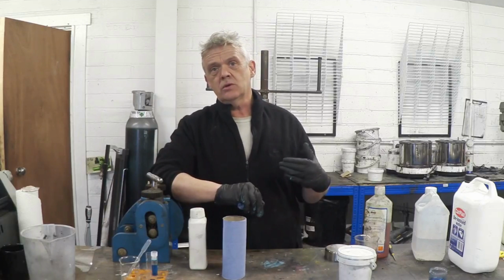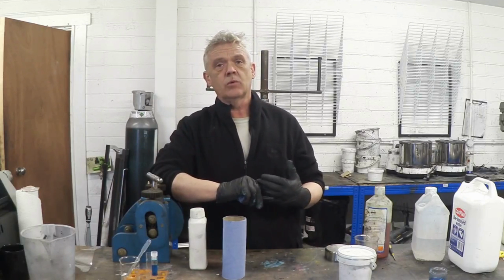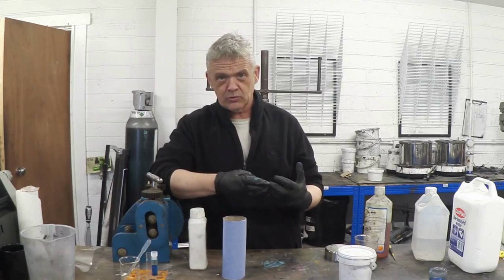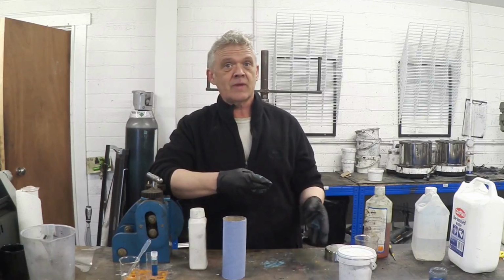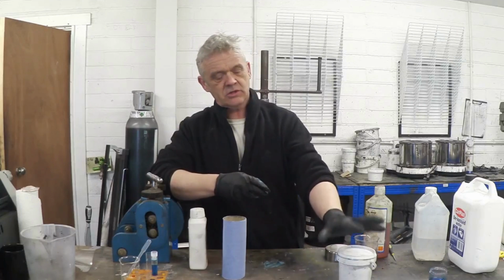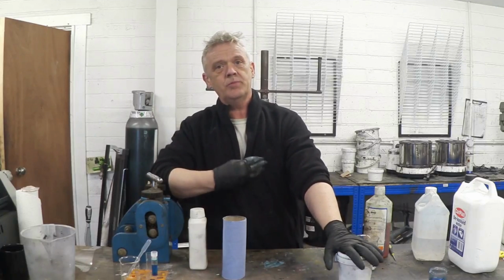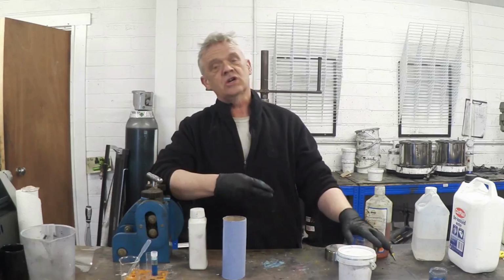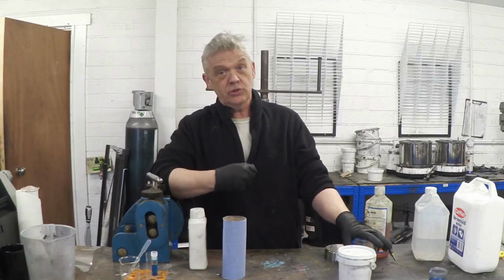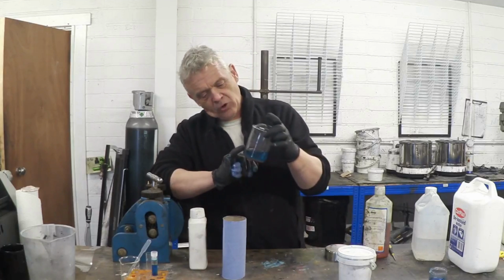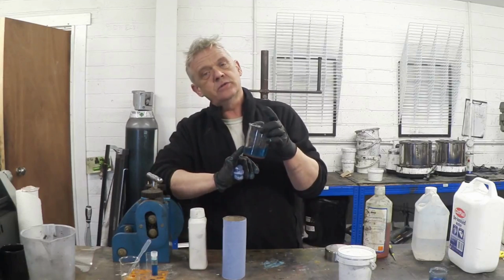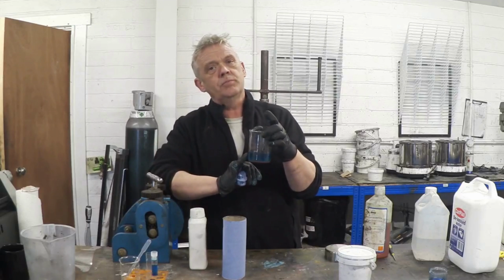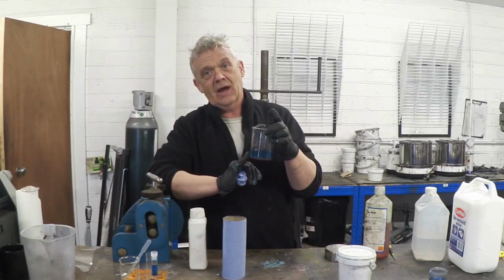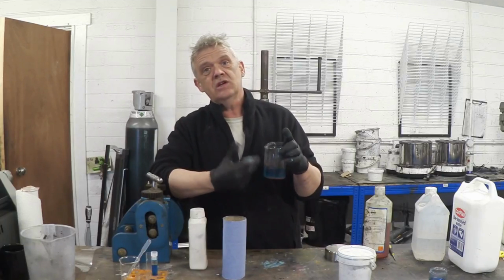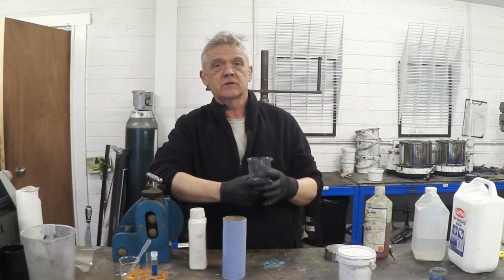Now, you just want to prepare the material when you want to use it, because they are small enough to oxidize quite quickly when they're in that particle form. So you take some of this material, which will keep your copper pure, add some water, decant it off, collect your particles and use them. Now, this formate here is really useful because under heat it will decompose into carbon dioxide, water and copper. And the heat you need isn't very high, it's about 200 degrees centigrade.